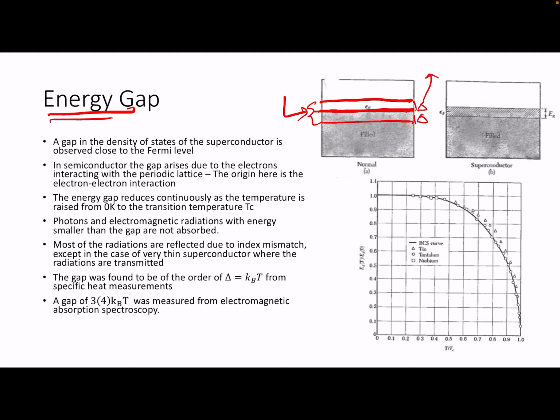This gap, which amounts to twice the delta, also varies with temperature. At 0 Kelvin, it has an energy of 2 delta, and as you increase the temperature from 0 to the transition temperature, this delta reduces, right? So basically it comes down, and the way it comes down is reminiscent of the Hc that we saw previously, right, in the magnetization behavior, the Meissner effect behavior. The critical magnetic field, that's what we saw, is the same way. The energy gap, the 2 delta, also drops down in the same fashion.